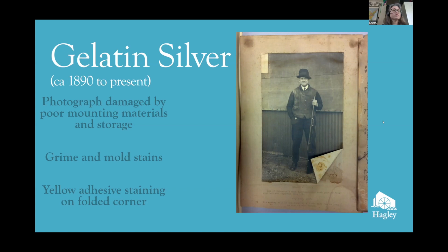The image can also be affected by acids and peroxides that may emanate from poor quality papers in which they are stored, or from wood that is nearby. Acids can also come out of wooden storage cabinets. The chemicals can also damage the paper base of the photograph, leaving brown coloration and embrittlement. So choosing appropriate storage containers consisting of acid and lignin-free paper envelopes, and boxes can help protect these photographs from damage.